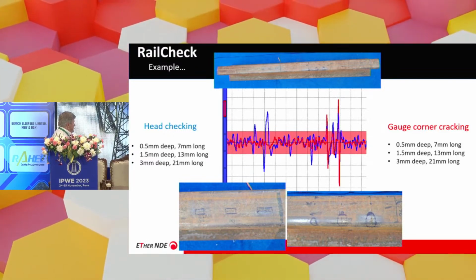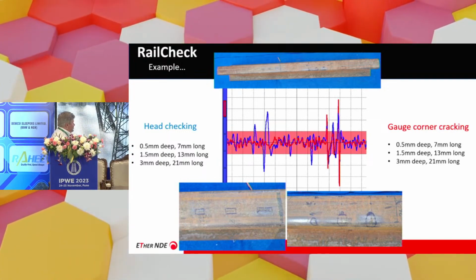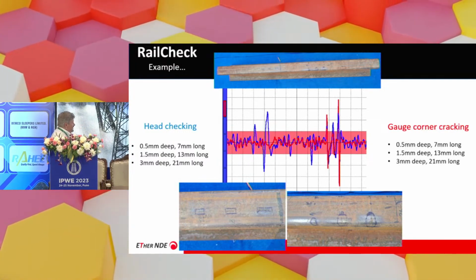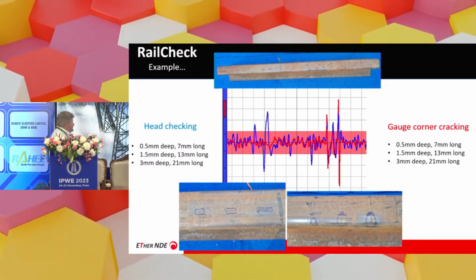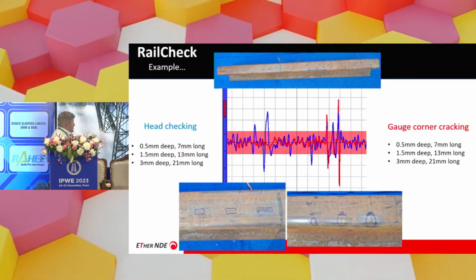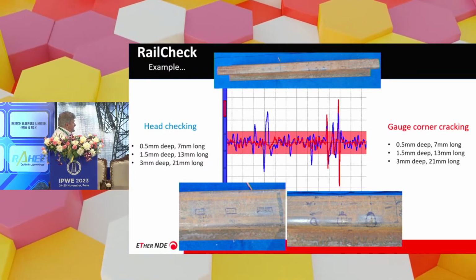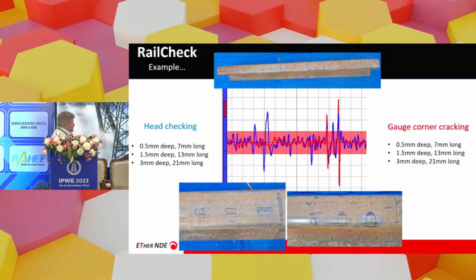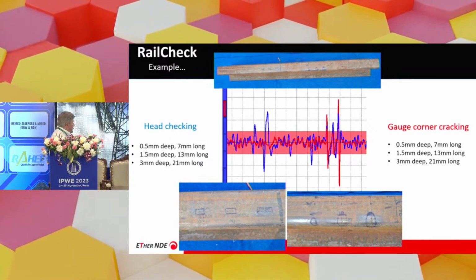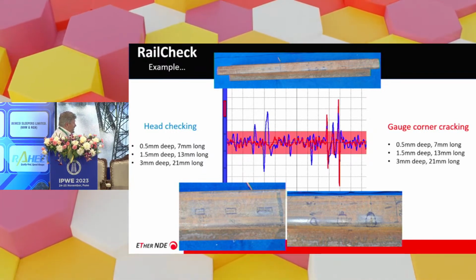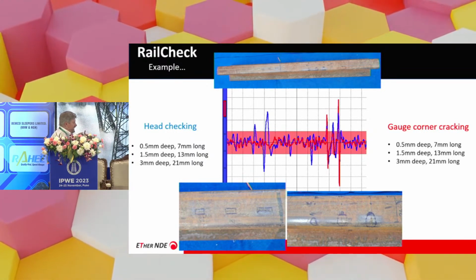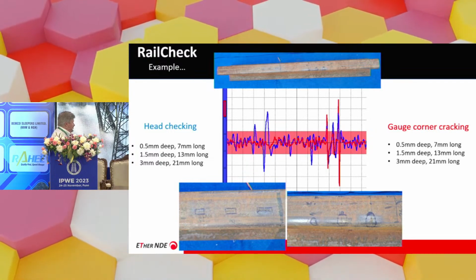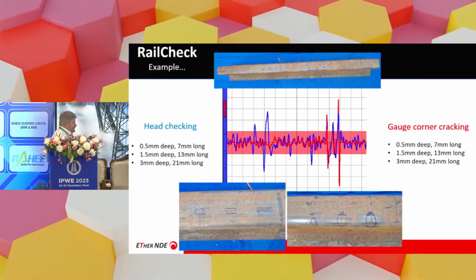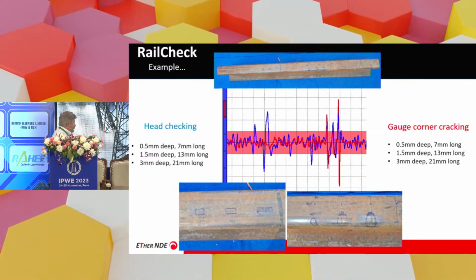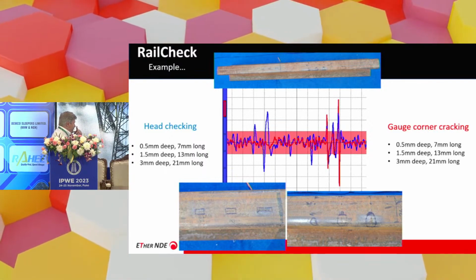This one's kind of hidden down here a bit, so it's not a brilliant output. That's the 0.5 millimeter deep by 7 millimeter long. And this we've probed around and it seems to be something to do with the rail still having magnetite oxide mill scale on it. It's a brand new rail that's never been used. It has quite a lot of corrosion on it, but that's not the issue.